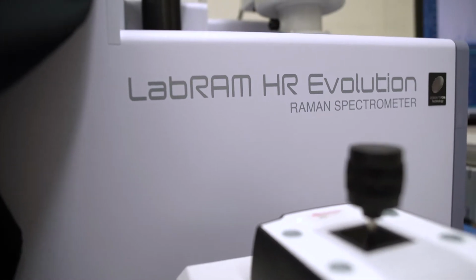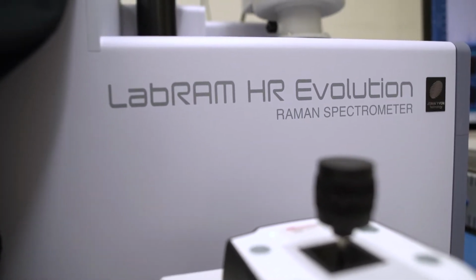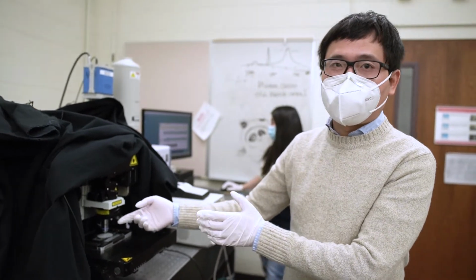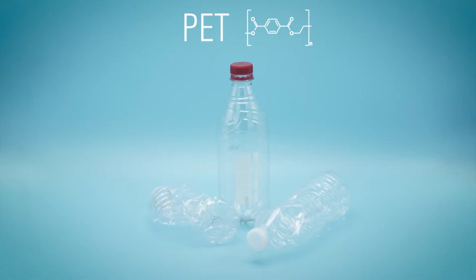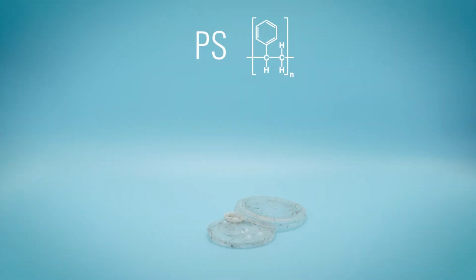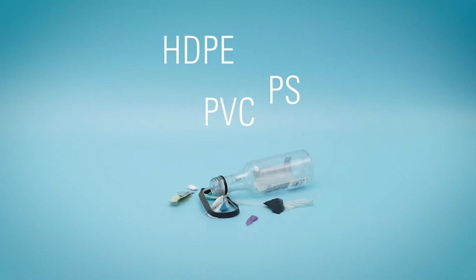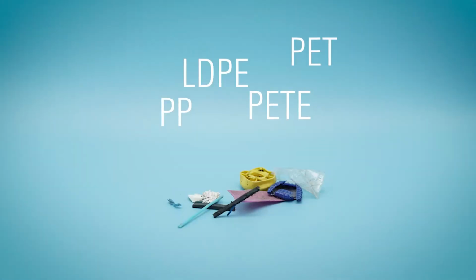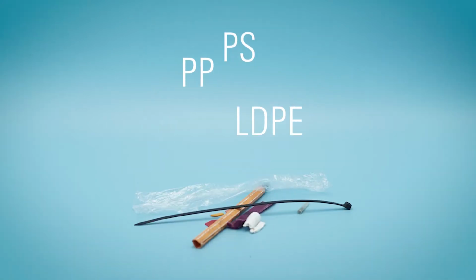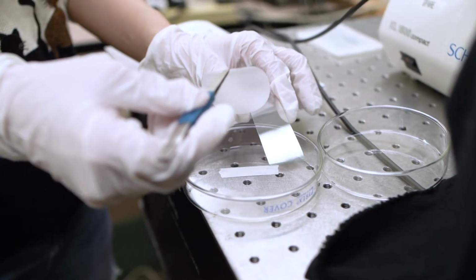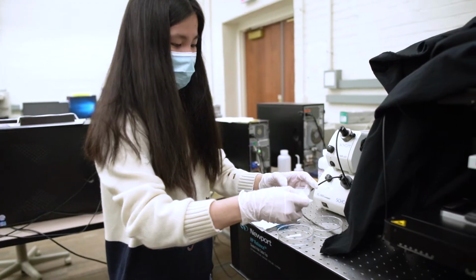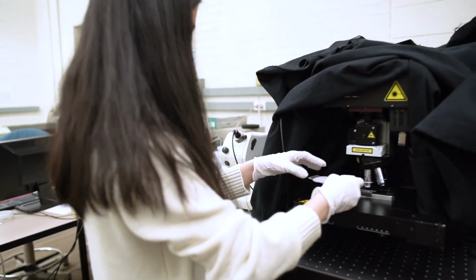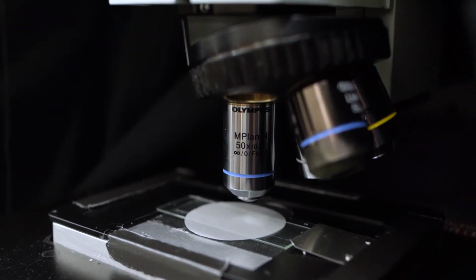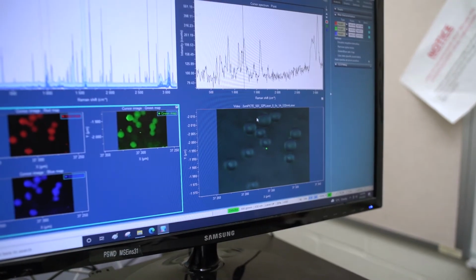Raman spectroscopy is used to identify the polymeric composition of these micro and nanoplastics. We have thousands of plastics, right? We have plastic bottles, the plastic packaging we use in fast food restaurants. Different plastics have different surface chemistry and they can undergo different degradation pathways in the water. That means they could have different toxicities. To figure out what the sources are, we need to know exactly what the composition is.